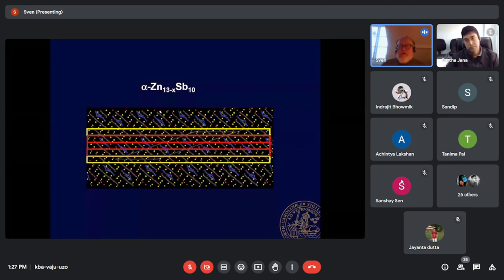superstructure low symmetry, it's actually triclinic. And the host structure is hexagonal, which means that you got 6 copies. But there is also an intergrowth between this and the pure phase, like in the doped crystal, so that there is a mixture of the high and the low temperature phases.